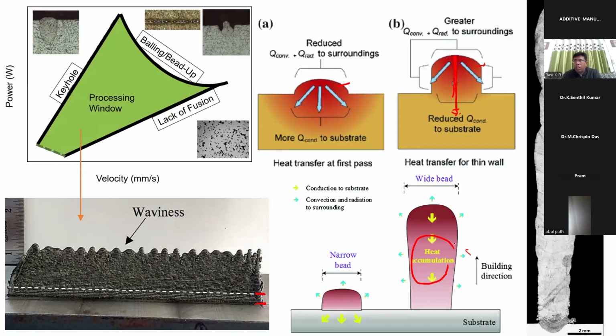If you look at here, when you start initially, you will have some amount of melt pool width. You see that the part is getting continuously deformed. It will start moving in a different direction. Those who have worked in wire additive manufacturing would see something like this. The parts would go this way. This is because of the heat accumulation.